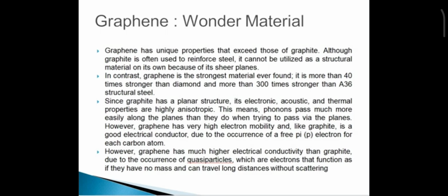However, graphene has very high electron mobility, and like graphite is a good electrical conductor due to the occurrence of a free pi electron for each carbon atom. However, graphene has much higher electrical conductivity than graphite due to the occurrence of quasi-particles, which are electrons that function as if they have no mass and can travel long distances without scattering. Graphene has a number of advantages over graphite, such as electrical conductivity due to the occurrence of quasi-particles.